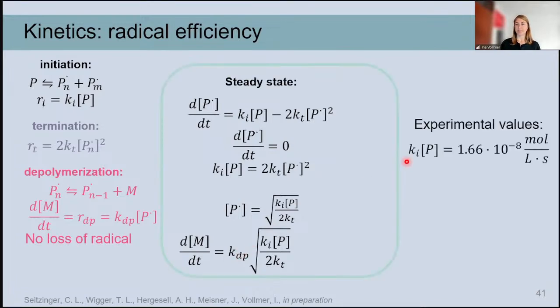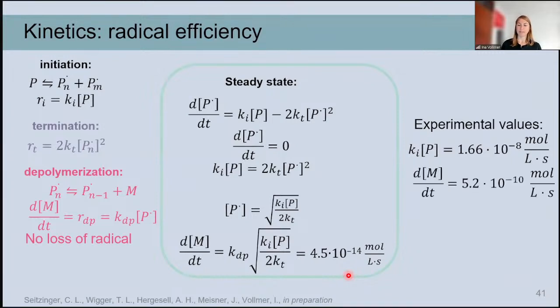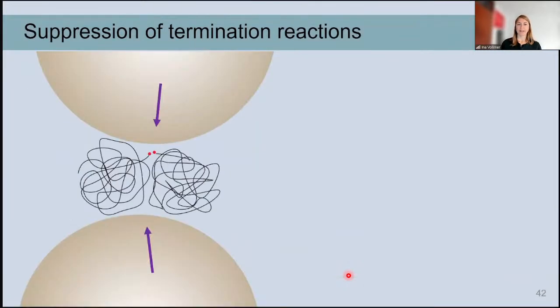In experiments, we observe these initiation rates, and this we can plug in here. If we then plug in the reaction rate constants from literature, we get this depolymerization rate or monomer formation rate. If we compare that with our experiment, we see that if we use the literature reaction rate constants, we would expect a much lower monomer formation rate than what we observe in the experiment. This is very interesting because it can tell us a bit about what is actually happening in the ball mill. What could happen is that in a very mixed reactor in solution, looking at radical polymerization, you would have the possibility of these radicals to recombine because the system is very well mixed.